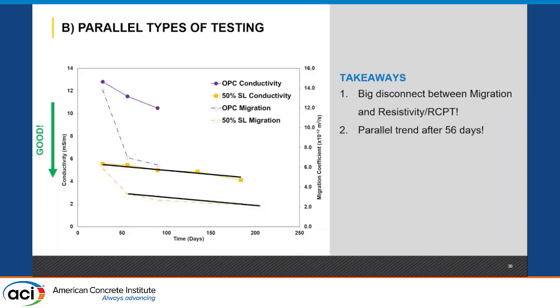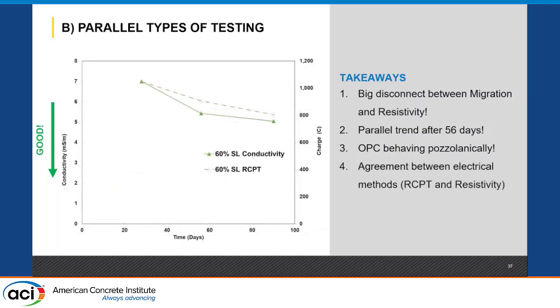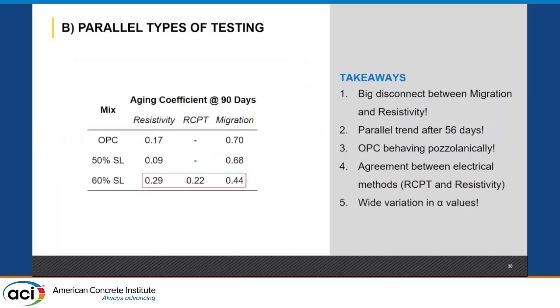So big discrepancy there. Something interesting, we see that there's a parallel trend between migration and resistivity, but it takes 56 days. So something about resistivity didn't capture this drop. And just a reality check, why is OPC behaving pozzolanically? The 4th takeaway is that there is agreement between conductivity and RCPT, which are both electrical methods. So that kind of hints at something going on with electrical methods. And in general, we see a wide variation between alphas, aging coefficients, and which test you do.